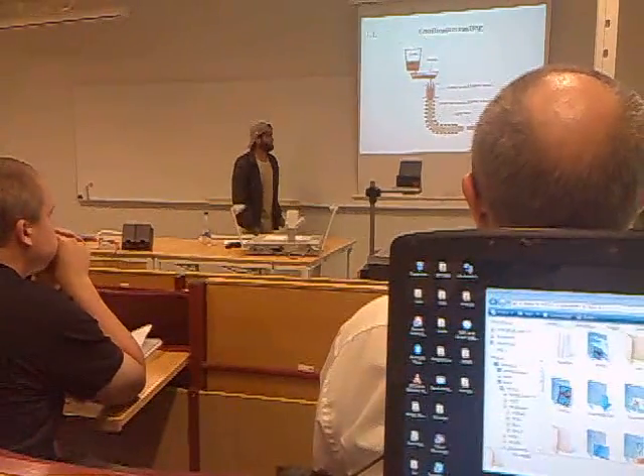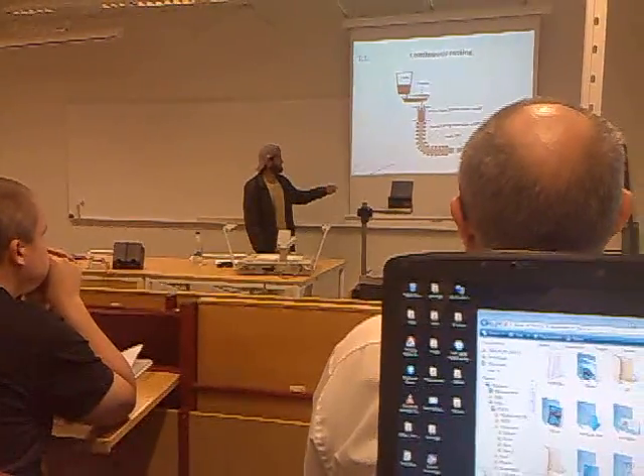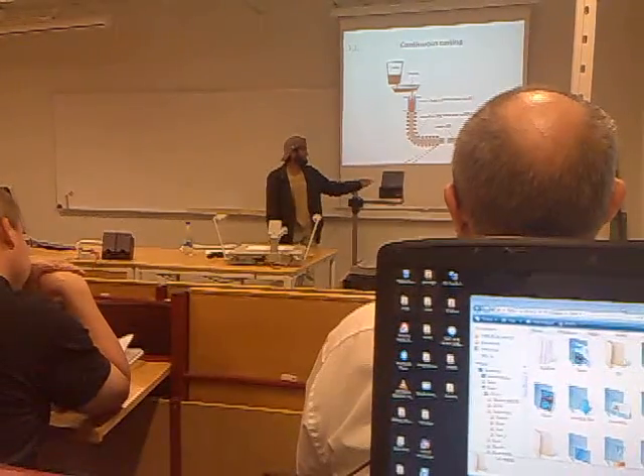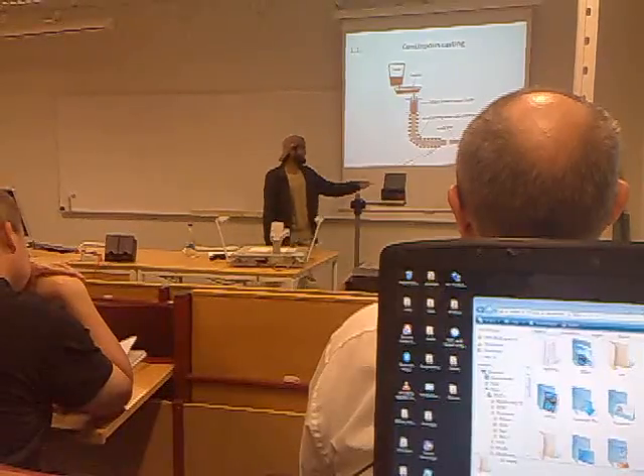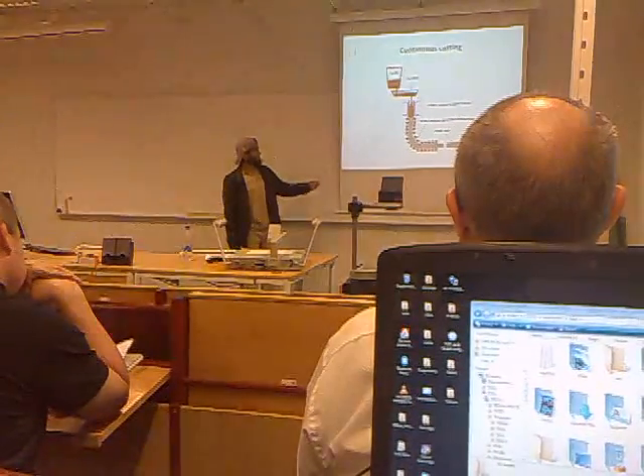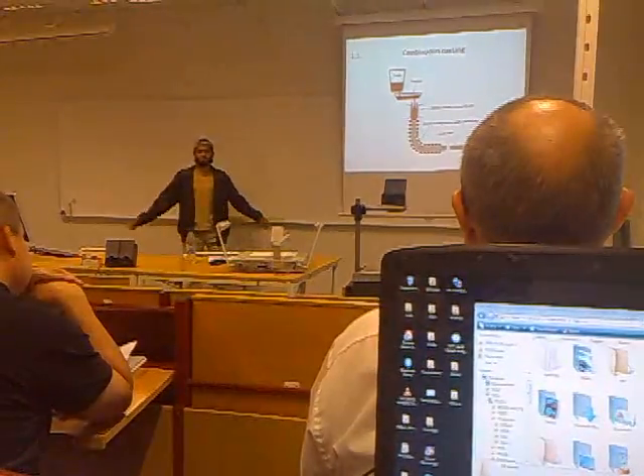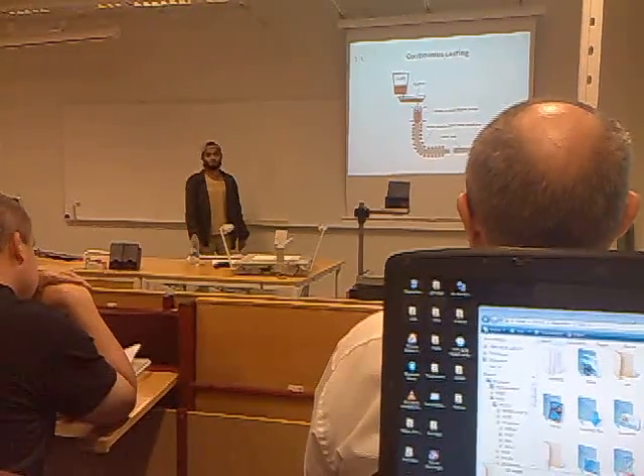Ladle tilted, and from there it goes down to the water-cooled copper mold, and steel strand emerges from this mold, which is not completely solidified, but once it reaches this area, this place, it's almost completely solidified. So here it is cut into pieces, and the process continues. It goes around the clock, and that's why it's called continuous casting.